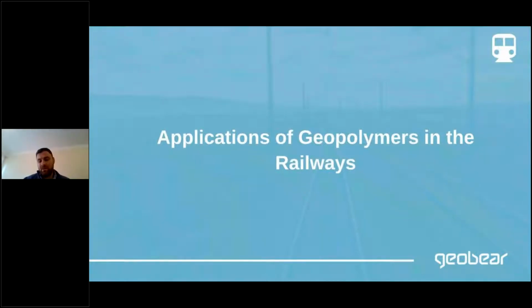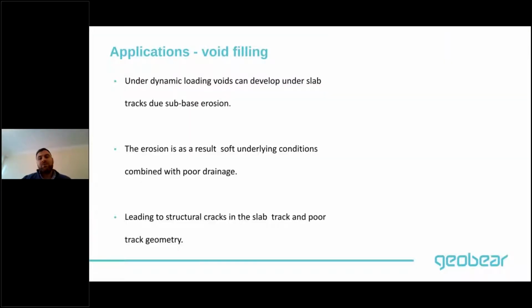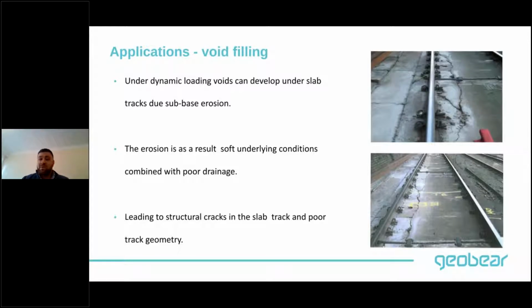Well, there are a number of applications. I've tried to highlight some of the most relevant ones to this forum. So the first application is the use of geopolymers in void filling, especially under slab tracks. Under dynamic loading, slab tracks can develop some voiding under the slabs. This is due to subbase erosion. The erosion is a result of soft underlying conditions combined with poor drainage. And as a result of these voids, you can develop some structural cracks within the slab, resulting in poor track